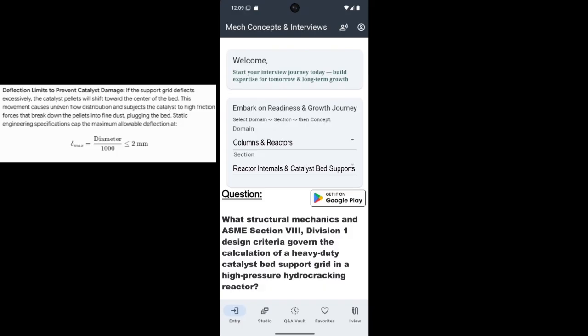Well, if the support grid deflects even 5 millimeters, it creates a physical slope. The catalyst pellets shift toward the center of the sagging bed. Moving downhill. Exactly. This movement causes uneven flow distribution, channeling the high-pressure fluids through the thinner edges. This channeling subjects the localized catalyst to incredibly high friction forces, violently pulverizing the expensive pellets into fine dust. Which goes where? That dust immediately plugs the bed. This spikes the pressure drop and forces an emergency, multi-million-dollar plant shutdown.